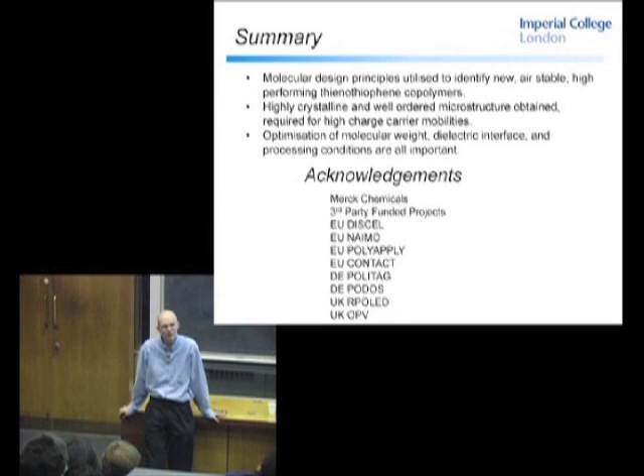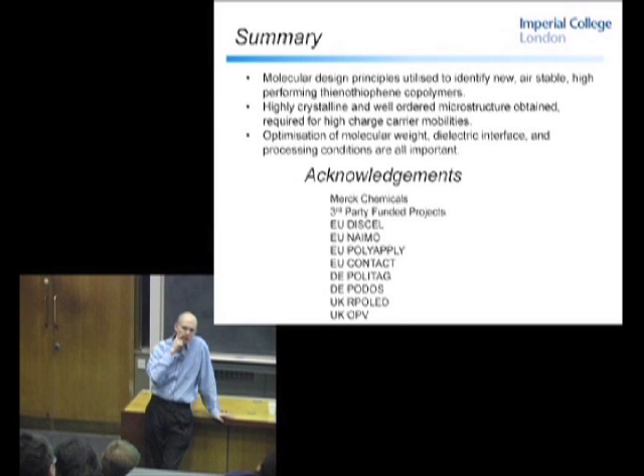The real problem is that although you have a mobility of 5 in the lab, by the time you manufacture, you introduce the fabrication compromises that you need to make, you might end up with a mobility of 0.5. So you've dropped an order of magnitude as you go to high throughput production. Then you're at the cusp of where you can do anything you like. But even now, with that type of mobility, it's enough to satisfy most first and even second generation ideas that people have for applications. That's not the issue.